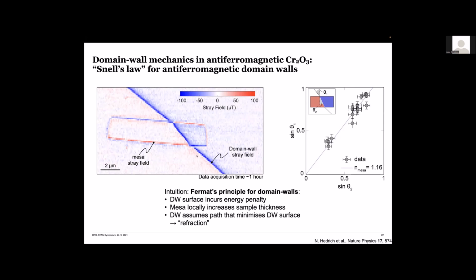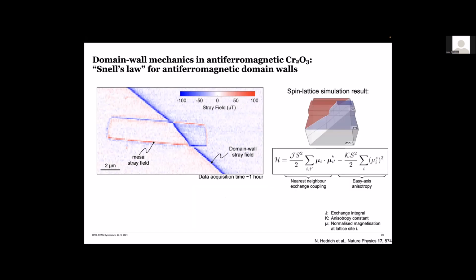And first, we were puzzled by that, but then in hindsight, it's actually rather easy to understand. This is just the analogue of Fermat's principle in optics here applied to domain walls. So the reason why you get this deflection is simply because the domain wall, of course, has an energy cost, and by crossing the mesa, the domain wall positions itself such that it minimizes the domain wall energy, or rather the domain wall surface. It's something we were able to also retrace or simulate here with a spin lattice calculation with some of our collaborators. So this is not a drawing, it's an actual calculation that matches very nicely this type of trajectory.